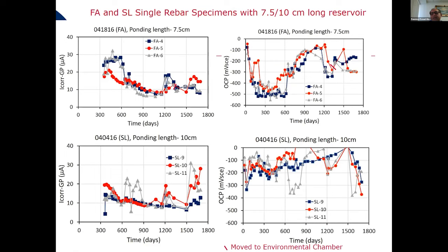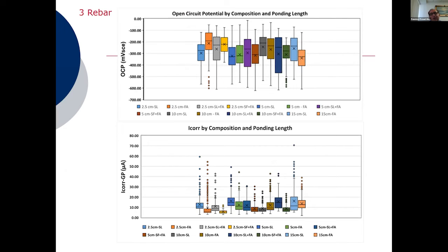And so that's for the red specimen in there. And also for the SL, you can see here that we have similar oscillation to what I showed you for one of the 3 rebar specimens, but not all of the samples are showing this big oscillation. Some of them have the downward trend that I showed you initially, but not to be repetitive, I only chose one of them.